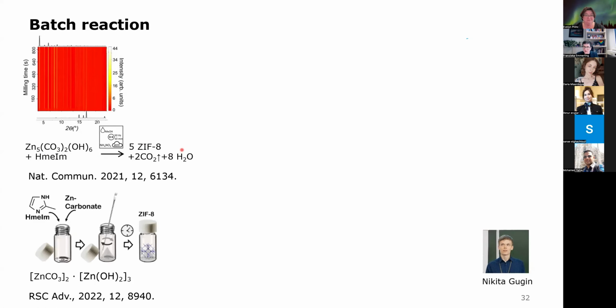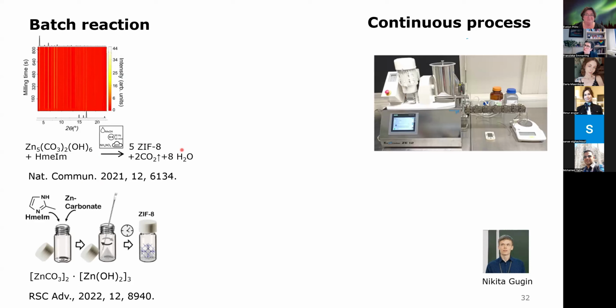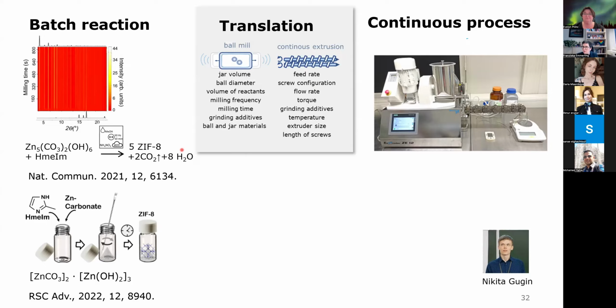We also found out that you can just stir it and keep it and wait, and then you can also get ZIF-8 in the end. So it seems to be quite easy on this mechanochemical route. But if you want to translate it to a continuous process, there are some things we need to think about. Usually you have parameters like ball diameter, volume of reactant, frequency, and so on. And here we have other variables that we need to translate it to, so flow rate. We have something like a screw configuration, the extruder size, the size of the barrel, and maybe temperature as well, and that can be adjusted here.